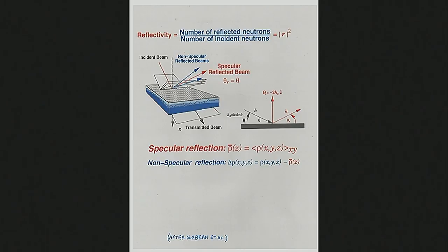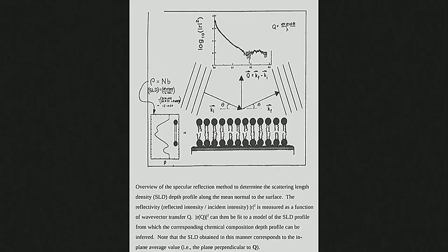Okay. So this slide is supposed to overview the paradigm, again, everything I just said in one slide. So if you control this experiment in the specular condition, you measure the reflected intensity, and the reflectivity is just the reflected intensity divided by the intensity of the beam coming in. And if you measure that as a function of angle, from lowest angle to higher and higher angle, or as a function of wave vector transfer, which is 4 pi sine of that angle over the wavelength, if you measure that as a function of the wave vector transfer,